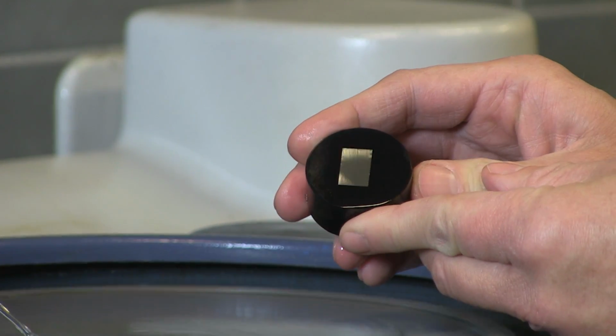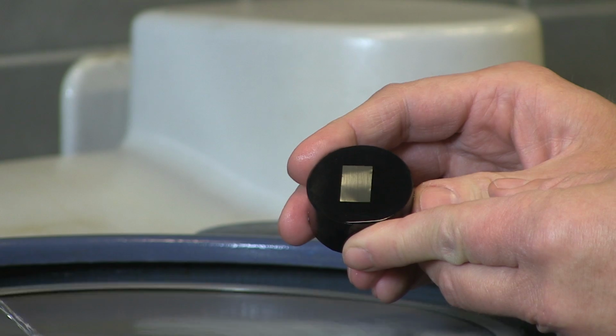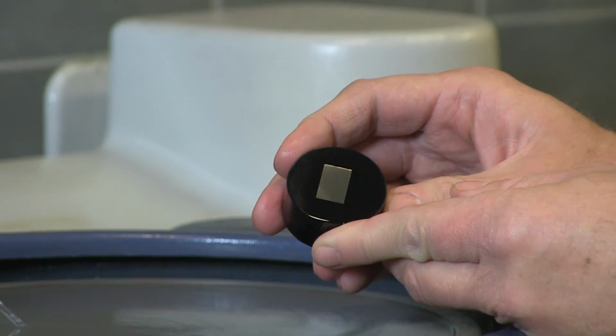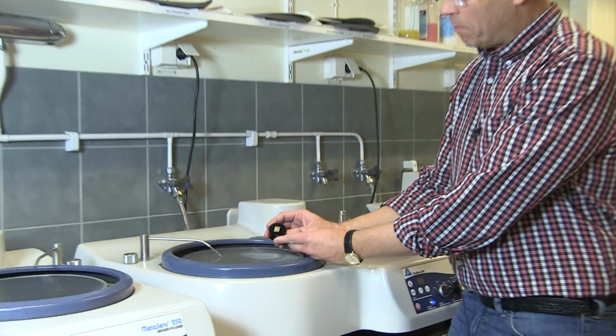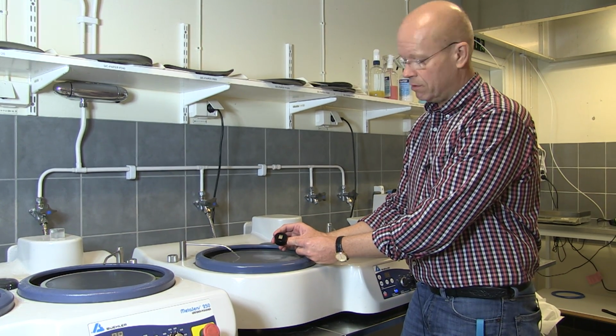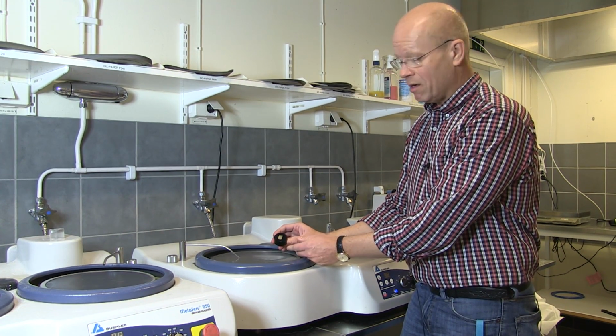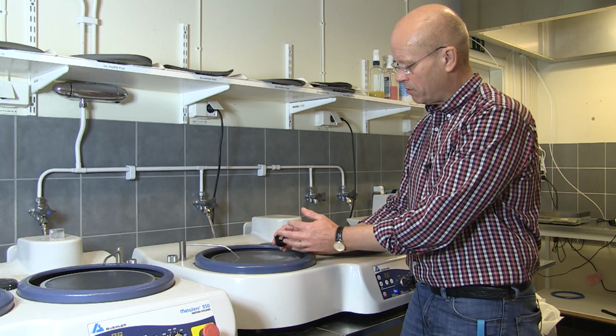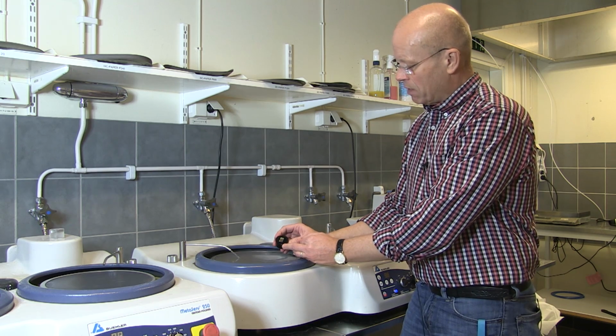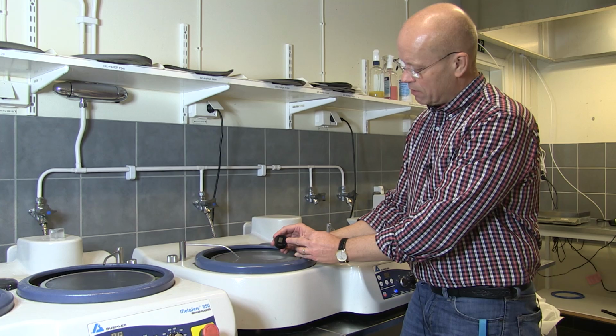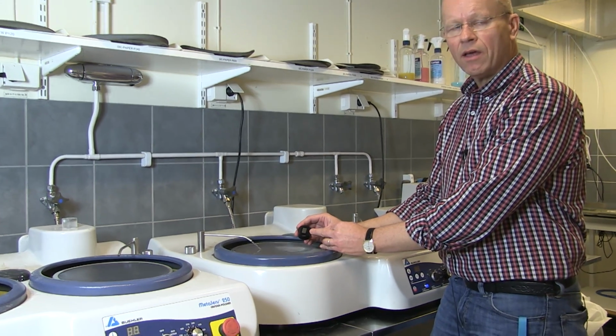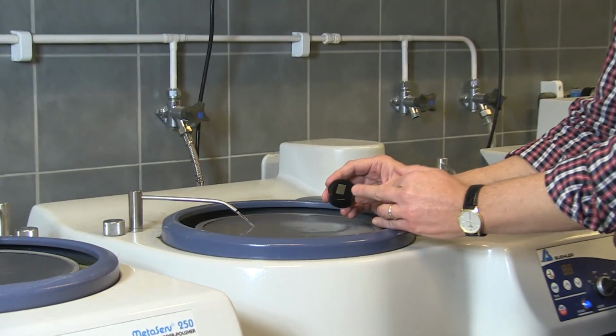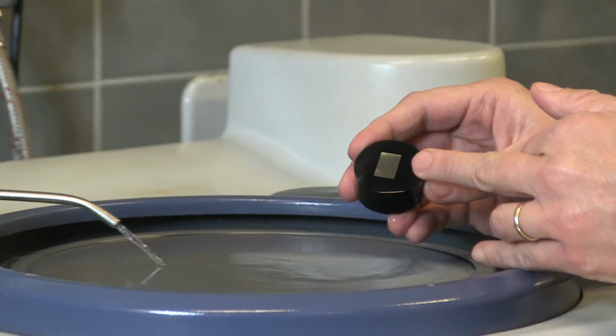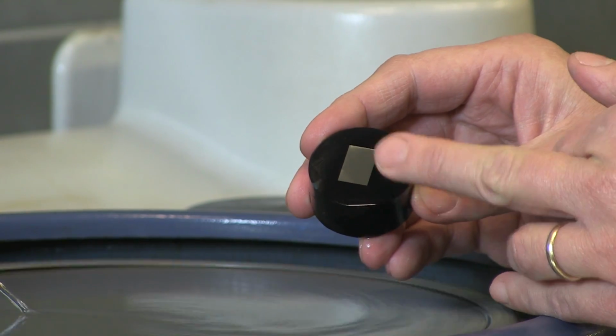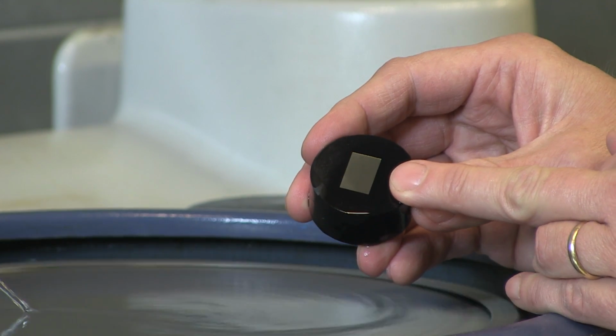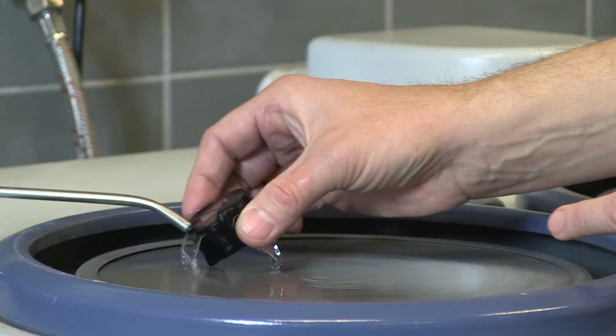You might be interested in how long time you should use for grinding a sample, and it's very difficult to answer that question. It depends on the size of the sample. Bigger sample, longer time. It depends on the hardness of the sample. The harder it is, the longer time. But a rule of thumb is that if you grind it until the old scratches have disappeared, at the same time you have removed not only the scratches but also the deformation underneath. But remember, it's a rule of thumb, it's not a truth. So, cleaning again, because I'm moving on soon.